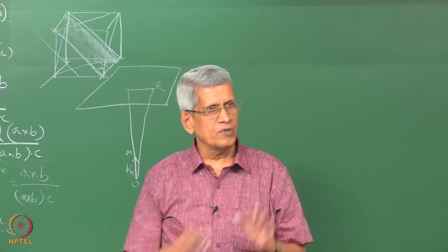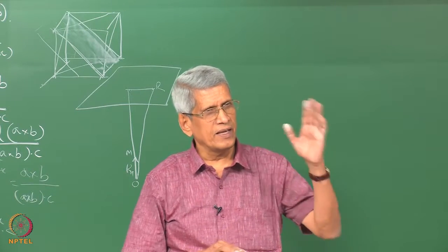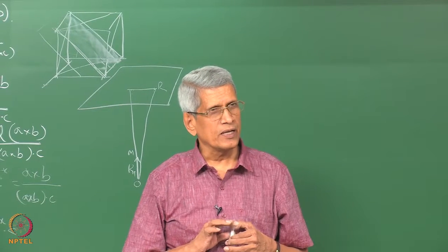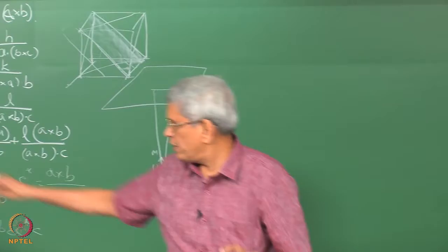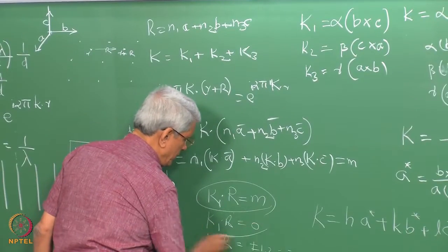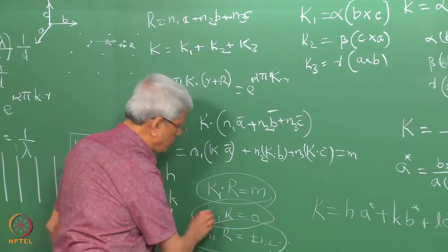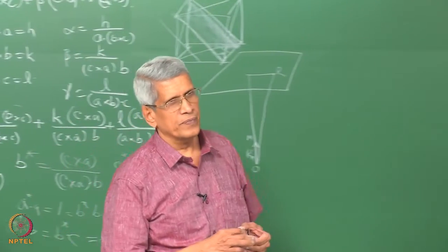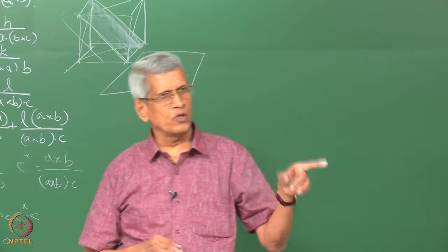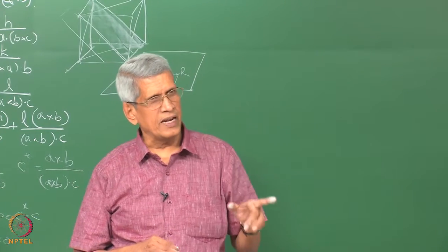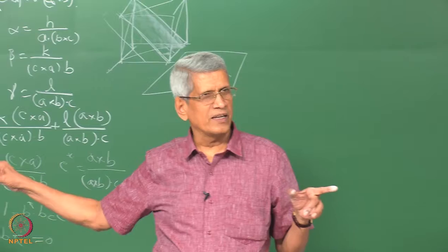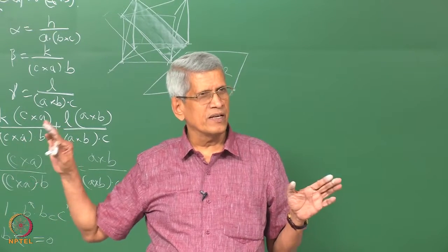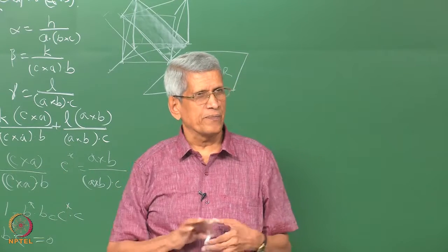So this is the condition which has to be satisfied between the real lattice and the reciprocal lattice. You understand that? What each of these expressions means is that, with respect to a particular reciprocal lattice vector which we have chosen, all the other vectors on different planes in the real lattice satisfy the condition k dot R equals m, that is, k dot R equals an integer.